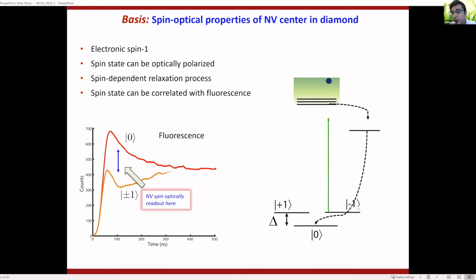But generally, the NV has a ground state, which is a triplet. It's a spin 1, and it's got an excited state. So it's got a collection of levels here at room temperature. And when you shine green light, you're actually shining light that's beyond the energy gap here. And if you start with the ms equal to 0 state, you do a cycling transition. So you go up and you come down. However, if you start with this ms equal to -1 state, you go up and come down, but with some probability, you go into a singlet state. And this singlet has two important properties. One, that it's non-fluorescent or non-radiative.